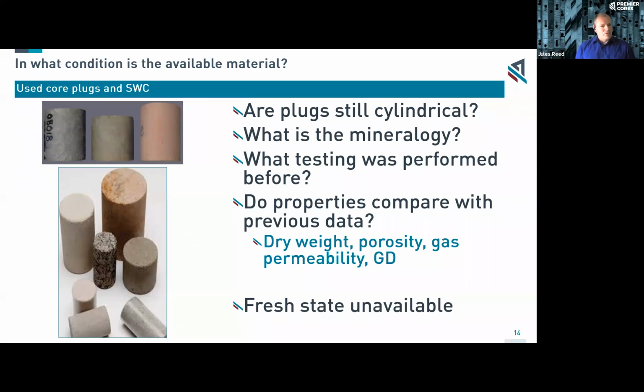Now, these previously used core plugs are going to be potentially better than an outcrop rock, as long as you've done the due diligence of ensuring that the properties are similar. But quite often, used core plugs can be used over and over again, and it's one of the beauties of analysis with clean state or restored state analysis. You can take a plug, clean it, saturate it, and measure the properties, then re-clean it, saturate and measure the properties again, and each time it should be consistent. It should be showing elastic properties, and should be showing no signs of hysteresis. If that's happening, then it's very easy to see that the sample can be used over and over again to show the reservoir properties and to be representative.